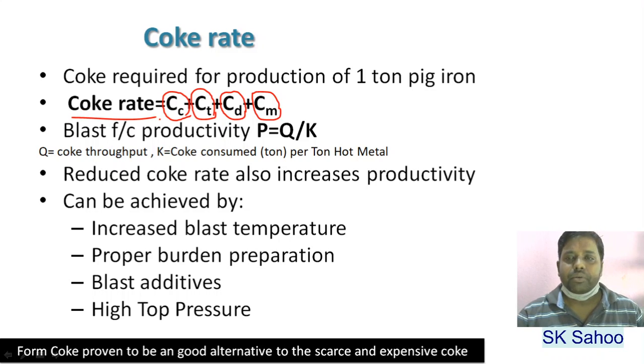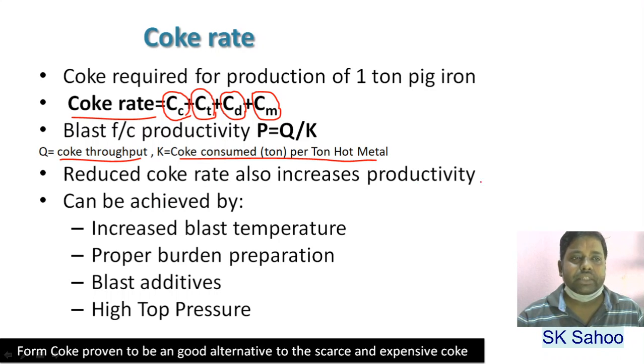We can relate the coke rate with the blast furnace productivity, that is P equals Q by K, where Q is the coke burnt per day, which is also called the coke throughput. How much coke is burnt per day? And K is coke consumed per ton of hot metal. K is the coke rate. So reduced coke rate also increases the productivity. We have to reduce the coke rate because the coke rate is in the denominator. If we decrease the coke rate, then it will increase the productivity. So how can we decrease the coke rate?